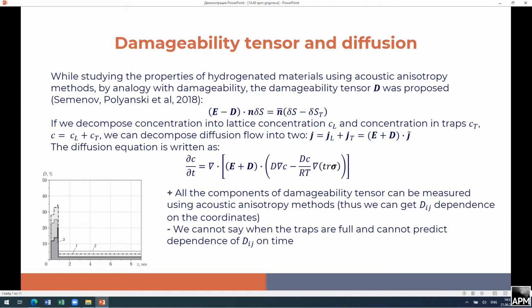So what we do, following all the researchers who are studying trap diffusion, we decompose our concentration into the lattice concentration and trap concentration. And thus we can decompose the diffusion flow. And saying that we don't have any equations or laws for the flow in the traps, it's just additional space for the hydrogen flow. We just obtain the diffusion equation with some addition.